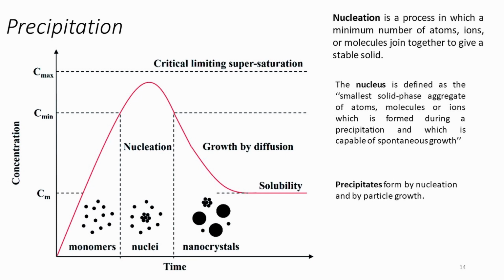A nucleus has been compared to a chemical reaction, and an activation barrier for this chemical reaction must be overcome. Therefore, it is necessary to create some degree of supersaturation before spontaneous crystallization will occur. It is evident that nucleation strongly depends on both concentration and temperature. If the nucleation rate is plotted as a function of supersaturation, a curve like the one on the slide is produced.